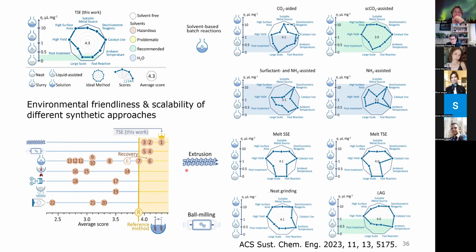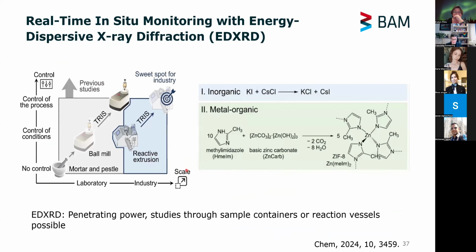Okay, so you can see in situ is always the link to understand what's going on in these reactions. And you have seen the steel barrel. There's another chance to look into the reaction, which we tested in a more recent work. So this trajectory is okay, but industry would like to have the extrusion in place and also know what's going on. And here we tested with energy dispersive X-ray diffraction. This is a clever method if you want to penetrate the whole reaction vessel, and you also get a snapshot of your diffraction pattern at once, and you can really study things through containers.